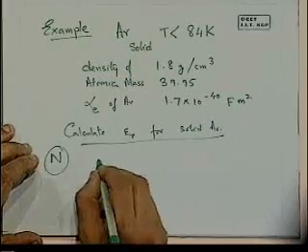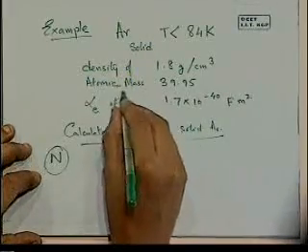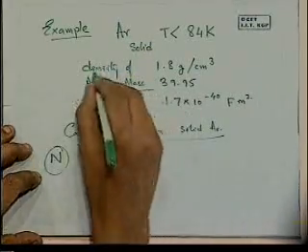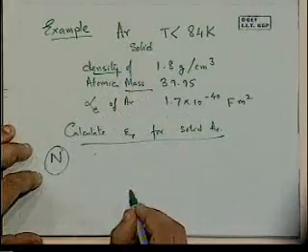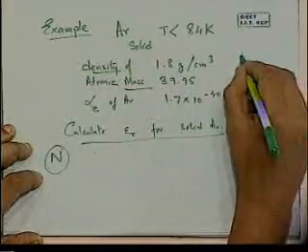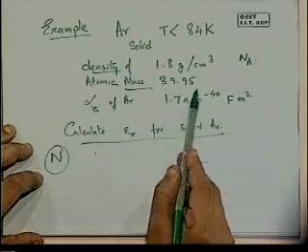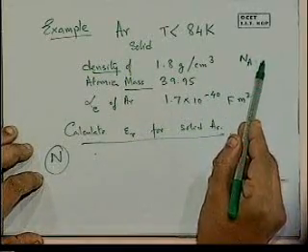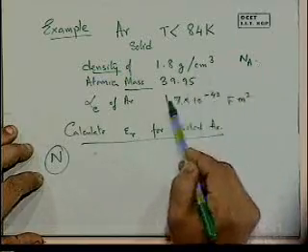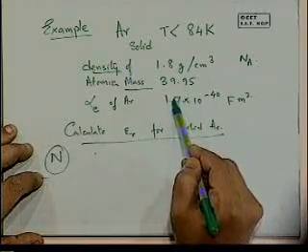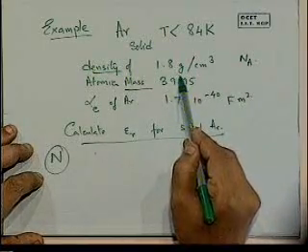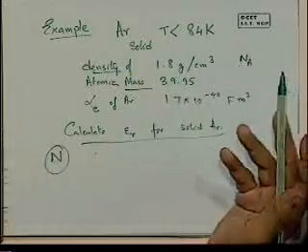And you can do that given the information about the atomic mass and density. You should be able to calculate the number of atoms given Avogadro's number. So 1 mole, namely 39.95 grams, contains so many atoms, and when you know how many atoms there are in so many grams, you can convert that using density into a volume. So you get the number of atoms per volume.